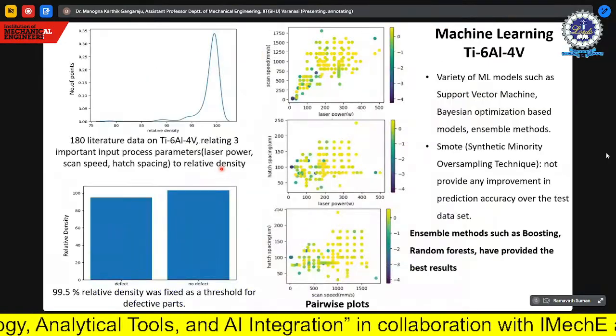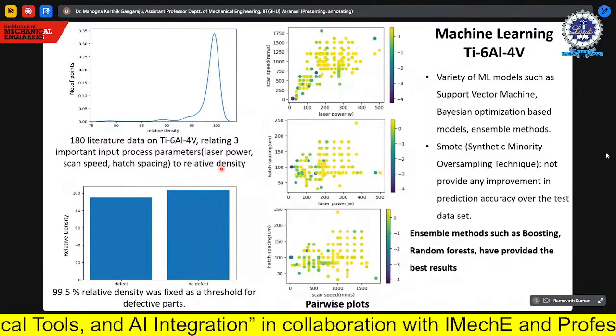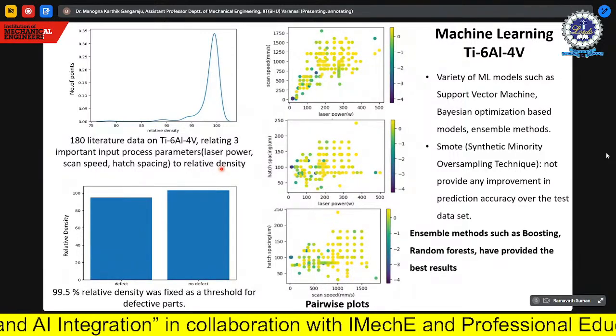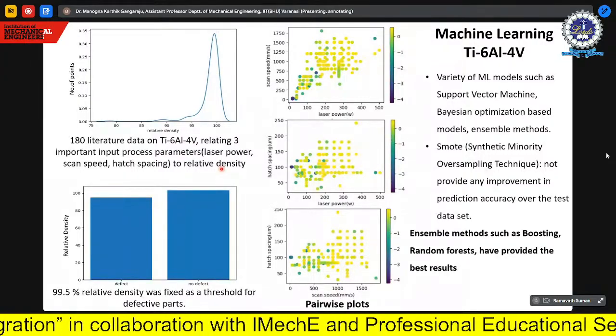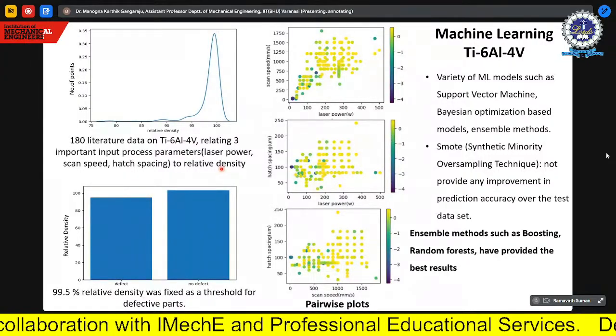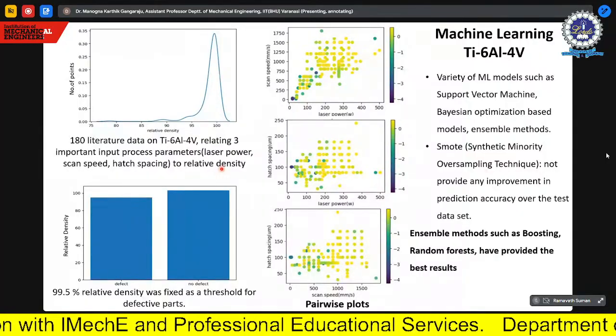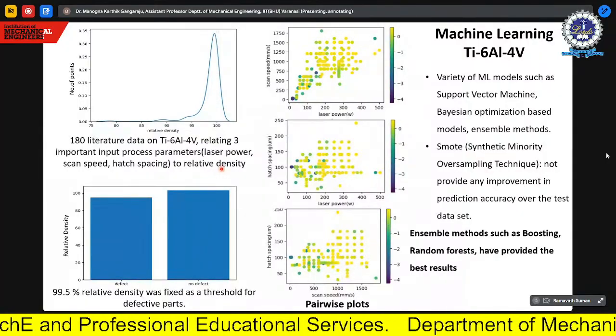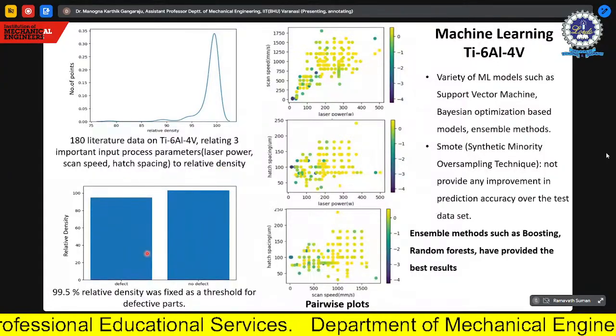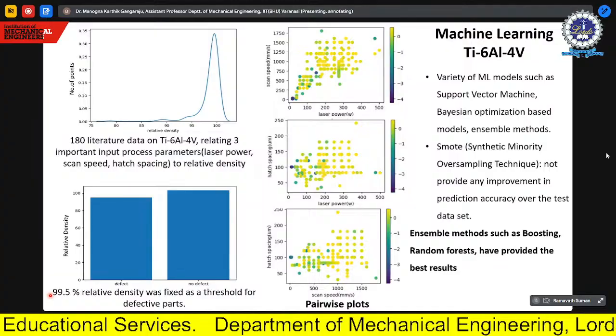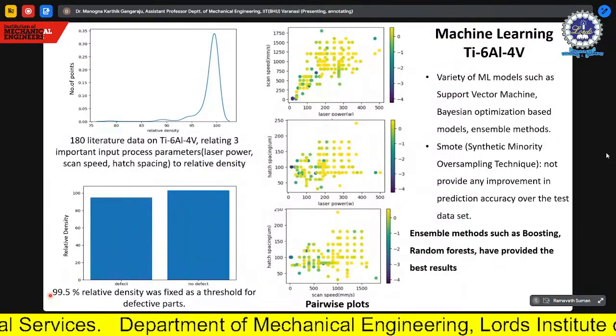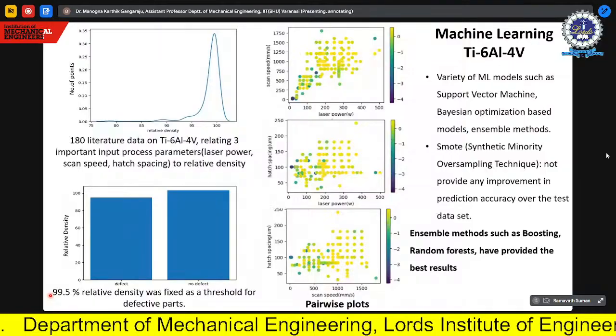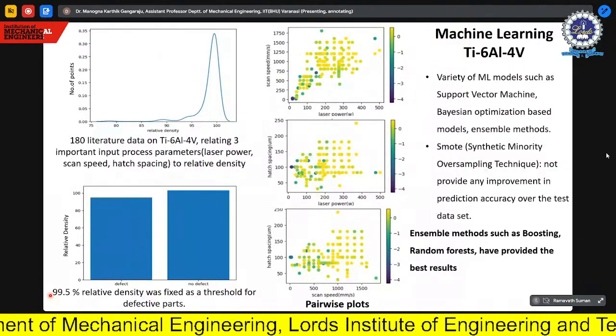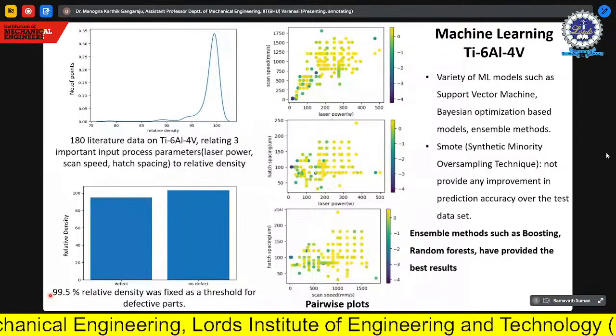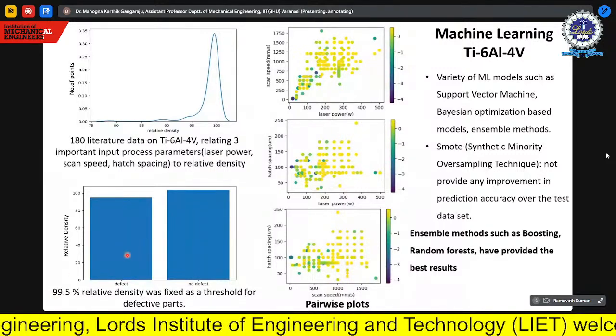So what we did is we did the same. We have taken Ti64 material. We could collect close to 180 literature data points. Okay, so we have collected data with respect to laser power, scan speed, and hatch spacing. So what we did is, any material or any report which says you have relative density 99.5, we consider that material as defect free. Any relative density less than 99.5, we thought it will have defects. So this is your data, with defects and without defects.